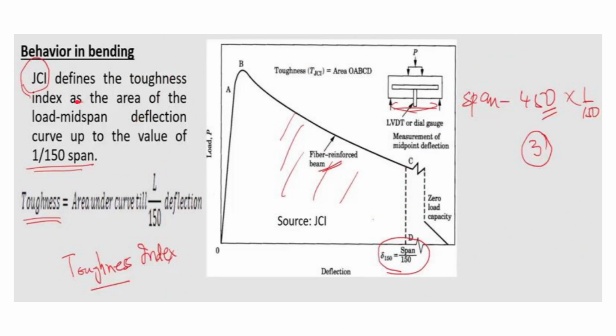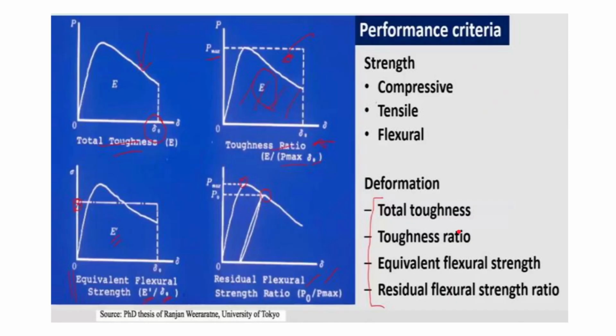In the case of Japan Concrete Institute, according to them, toughness is measured by the area under curve till L by 150 deflection. Okay, that is span by 150. So various criteria can be used, and based on compressive tensile flexural strength, various deformation parameters have been defined, such as total toughness, as you can see here, E, toughness ratio, that is total toughness E by P max into delta naught. Okay, equivalent flexural strength, which is equal to E prime by delta naught. Okay, and residual flexural strength ratio, which is equal to P naught by P max.